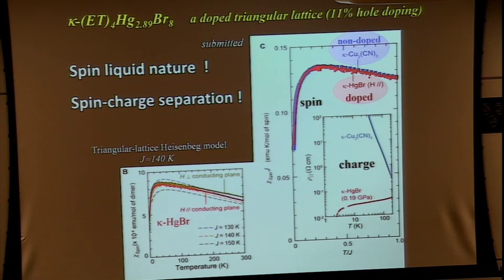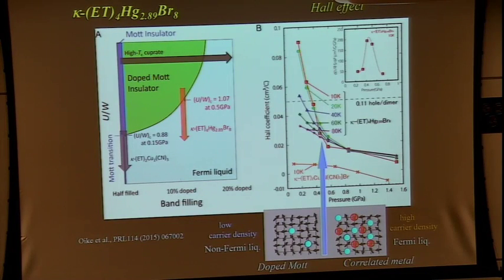This is very recent data, unpublished. This is the pressure experiment of the Hall coefficient as a function of pressure. Okay. And please take a look at the low temperature data of the Hall coefficient, like this. At low pressure, the Hall coefficient is very high. This means that there are very few carriers. But at high pressures, the Hall coefficient is decreasing to a very low value. Some crossover occurs around 0.5 GPa.